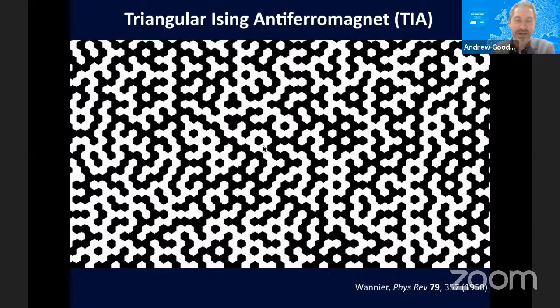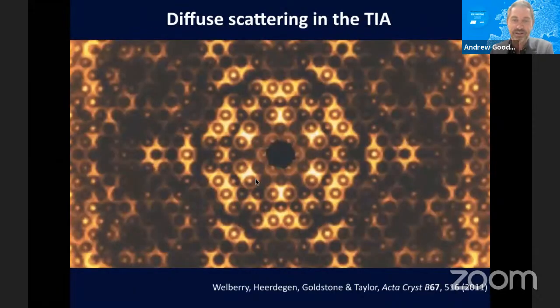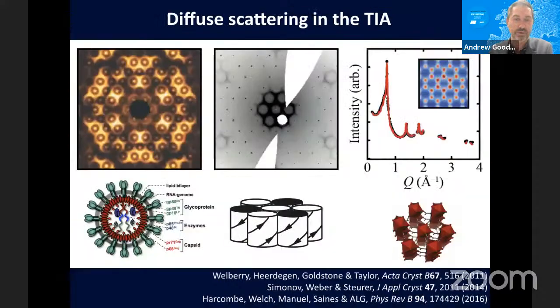So there we are. This is one of those disordered states we were just talking about, neither random nor ordered. The diffraction pattern for these sorts of systems looks something like this, where you have a Bragg component from the underlying periodicity of the triangular lattice and a diffuse component that captures information about that disordered state. And of course, as you know, the rule of thumb with diffuse scattering is that if you have it in the diffraction pattern, you've got disorder. And if that diffuse scattering is beautiful, then the chances are the origin of that disorder is also beautiful.